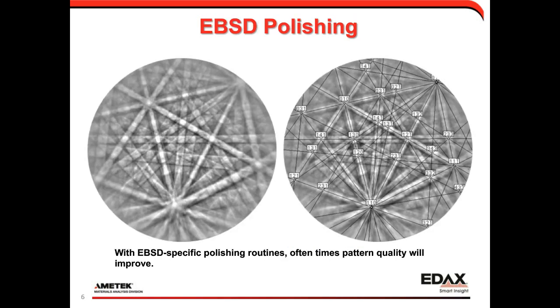So if we look at an EBSD pattern from the same material, and this is a zirconium oxide sample here, and we adapt our polishing routine to what I'd call an EBSD-specific polish, we see that the pattern quality improves. In the pattern here, the bands become a little bit sharper. We can still index just as well, but the quality of the diffraction has improved a little bit.